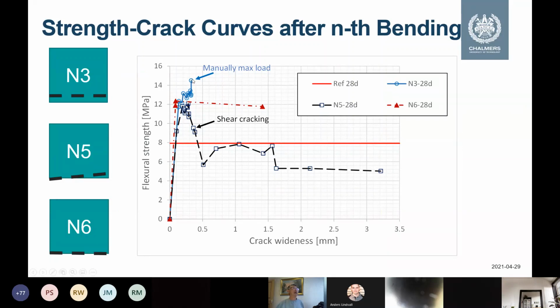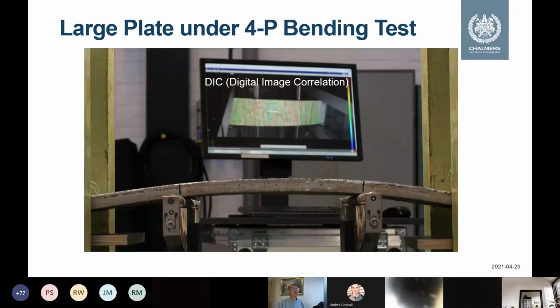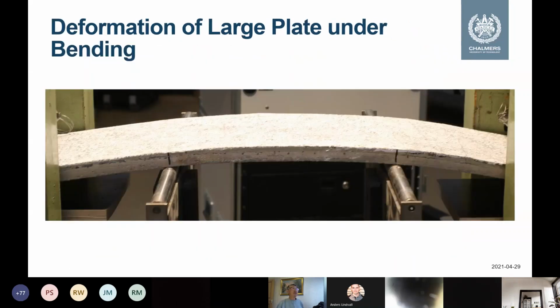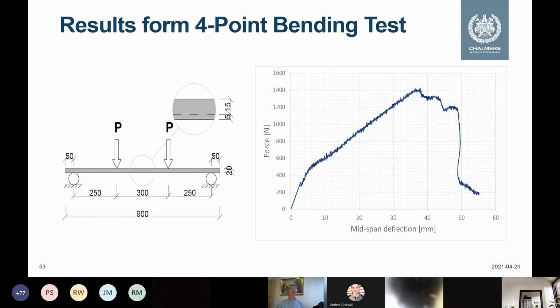This is the curve. After maximum loading, we have about 15 megapascal flexural strength, and the crack is just about 0.3 millimeter, which I think is quite good. We also did large plates in 4-point bending. You can see the digital image correlation. The cracks are very well distributed, and the plate bends about 5 centimeters, so it is really a bendable plate. In the curve, the force can be kept up to 40 millimeter, and until 50 millimeter it becomes broken.